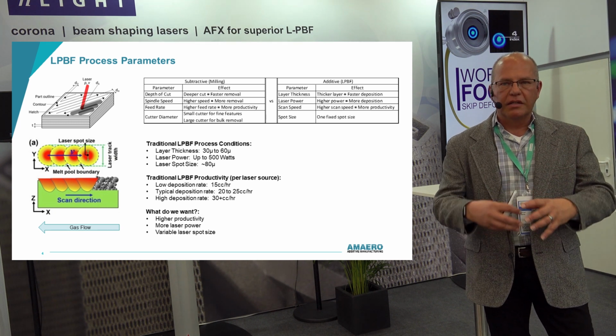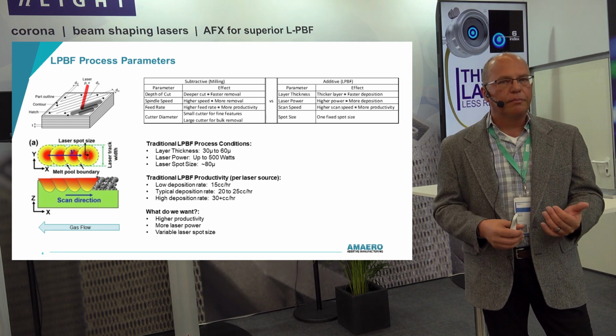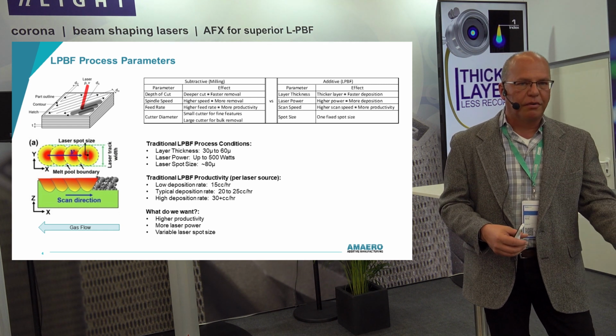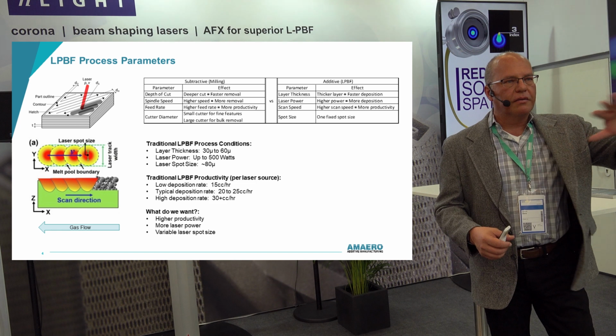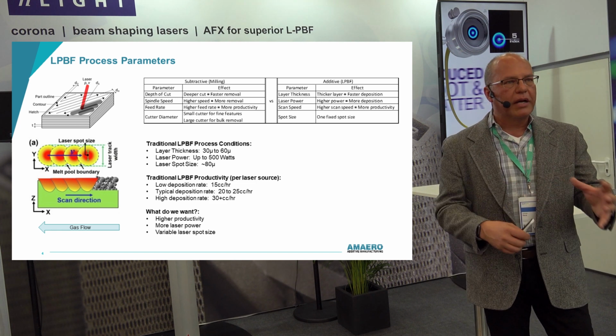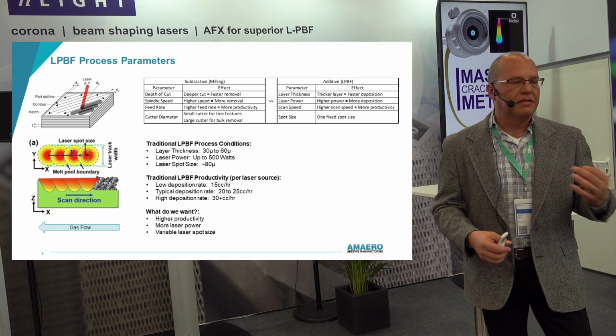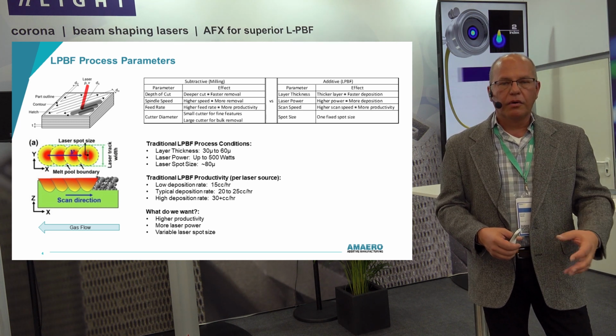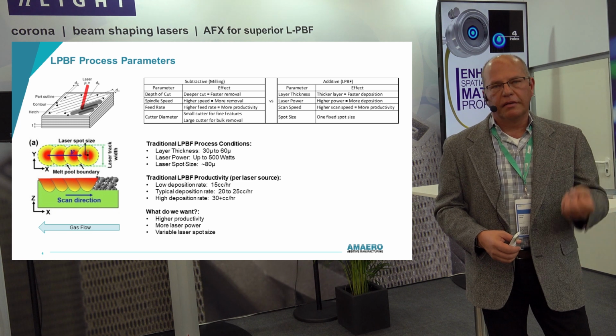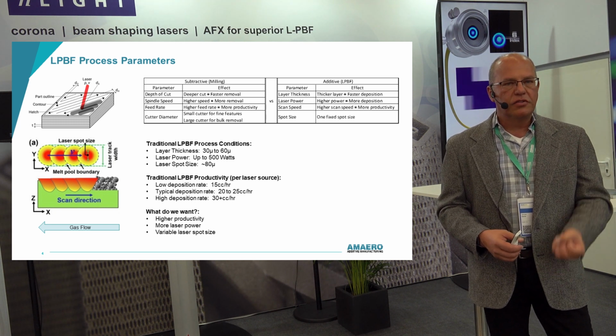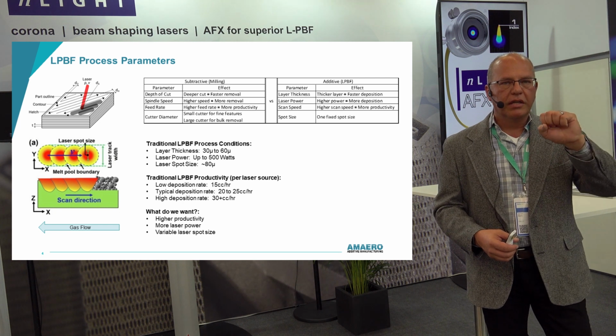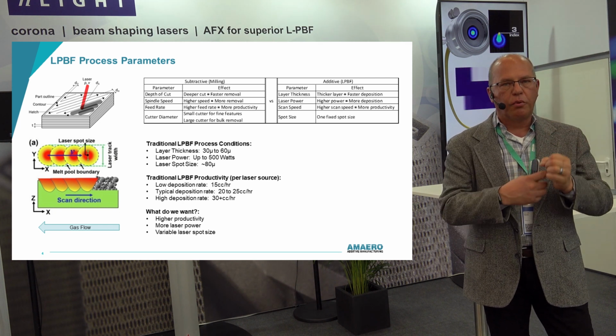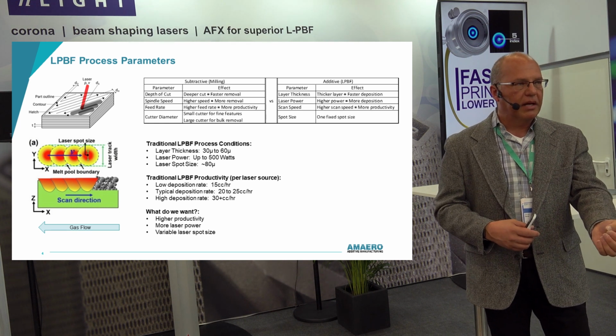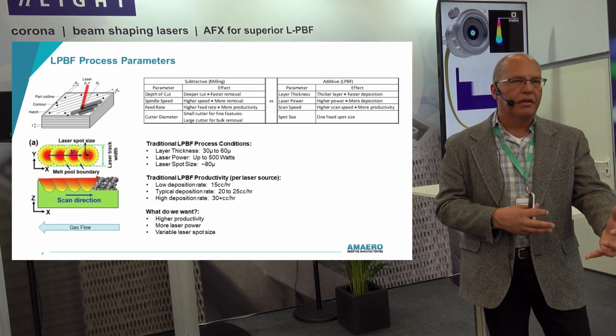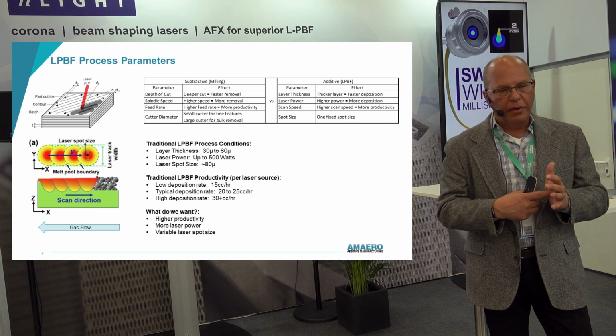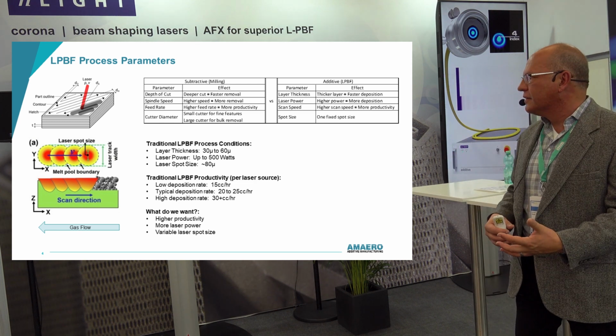It consolidates in the chamber in the form of very fine particles, submicron particles, pyrophoric particles. They are jumping around in the atmosphere. They're causing laser obscuration by getting in the way of the laser beam, which results in defects on the melt bed. And then we're also creating a lot of ejection of molten material, weld spatter. As that jumps out of the melt pool, it coalesces into a very large ball with a gas pore in the middle, drops back down on the bed, and we might weld it in, we might not. It's kind of big, and it's going to have a void in the middle of it. So this all generates a lot of defects.